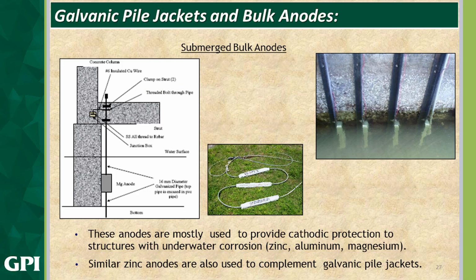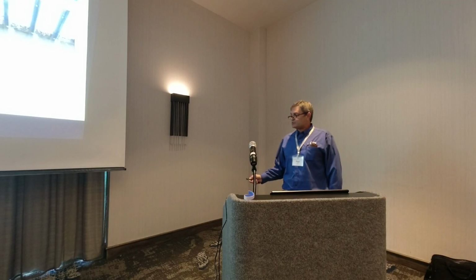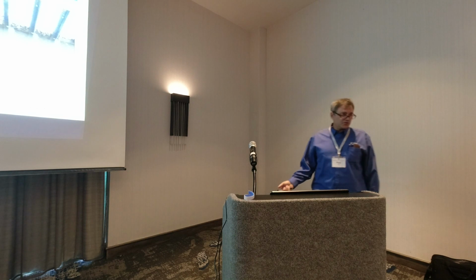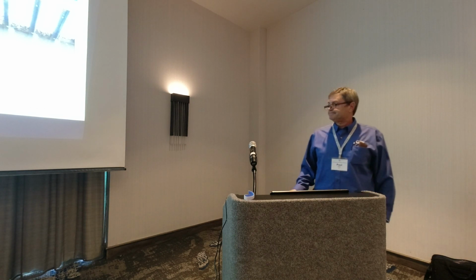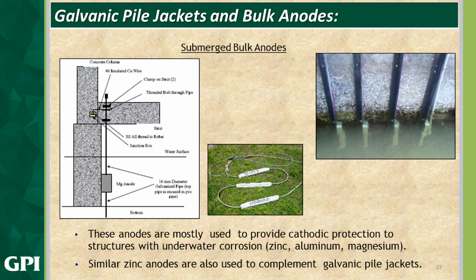Here's a picture on the right of some submerged bulk anodes hanging on, I can't tell, it looks like channel. These anodes are mostly used to provide cathodic protection to structures with underwater corrosion. Magnesium is more for fresh water, and zinc is mostly utilized in salt water. Similar zinc anodes are used to complement galvanic pile jackets. Again, we use the pile jacket in the splash zone. We use the bulk anode below the waterline.